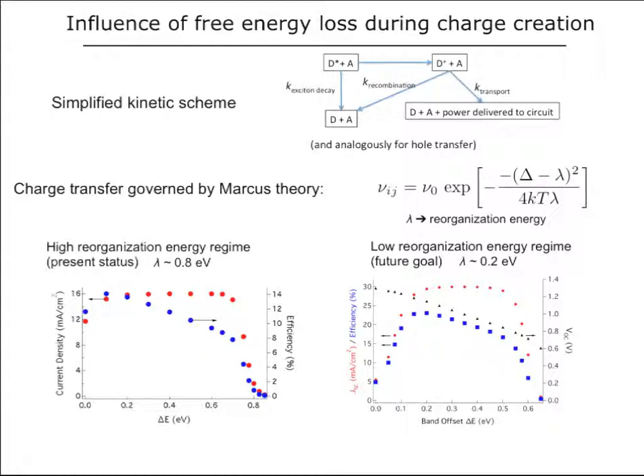And as you reduce delta G, you see that efficiency goes up because voltage goes up, but it'll crash at some point because the driving force becomes too small. And in this regime, we can get efficiencies something around 8% for this large delta G, and maybe up to about 12 to 14% for small delta G.